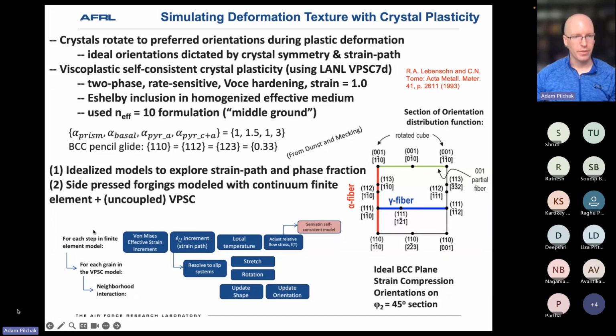and then we did that uncoupled version with the finite element step. The one thing I did want to point out, typically these are done as isothermal calculations, but we know that in titanium alloys, as phase fractions change, there's a change in the strain partitioning between the primary alpha and the deforming beta phase. And so we introduced a self-consistent strain partitioning model that Lee Semiatin had developed. And we also introduced a transient thermal analysis that would account for the effect of deformation on accelerated diffusion and its effect on the primary alpha dissolution during